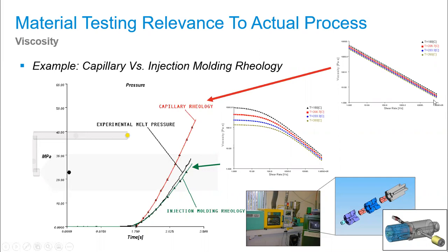So really with injection molding rheometry, we're getting those accurate points where quite frankly, a lot of the injection molding is done. We typically don't see most people going slower and using lower temperatures in the regimes down here. But as we get to the end of packing, we definitely can get gate freeze-off and those types of things better with injection molding rheometry as well. So it serves both purposes: getting us better on the higher ranges and also on the lower ranges as well.